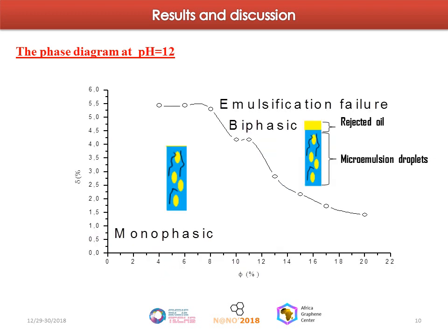So at pH equal 12, all the acidic groups on the PAA chain are ionized and the polymer is fully charged and in its most expanded state due to the electrostatic repulsion between the neighboring charged monomers, and the charges on the drops allow for bonds of electrostatic origin.